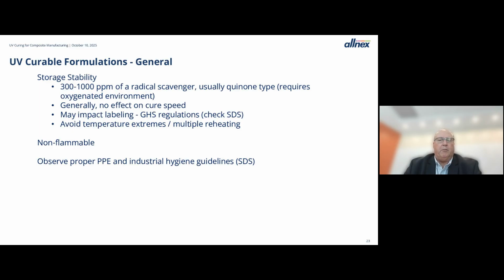And then a couple general comments about UV formulations. Pretty much every UV curable material, every acrylate or methacrylate, will have some type of radical scavenger in it at the 100s of ppm level. They're generally quinone types, and these help prevent premature gelation or reaction. Key thing to note is that the quinone type requires oxygen to work. So a lot of people have a desire to nitrogen blanket materials or to put an inert atmosphere over partially used drums or full drums. Don't do that here. That will render the radical scavengers or the stabilizers inert and greatly increase the chance of prematurely gelling your batch. So dry air is great, lean air is great, but there's got to be some oxygen in there for the radical scavengers to work.